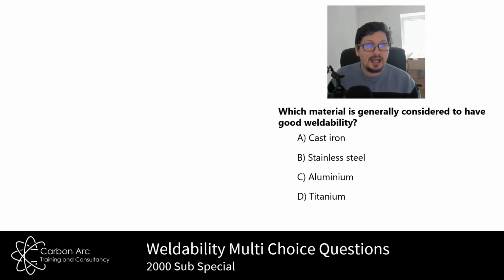Well, it's got a high carbon content, multiple percentage points of carbon. Therefore, it's probably a low weldability. If you try and weld cast iron, very often it cracks, and that's all. It doesn't work. You need very, very high heat inputs, very, very slow cooling rates to really have a chance. And some grades just won't weld at all.